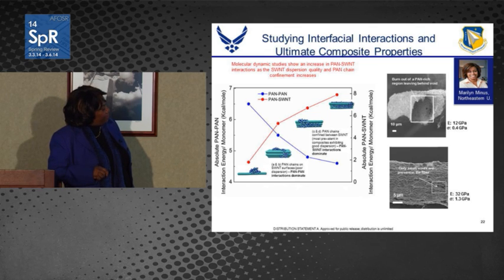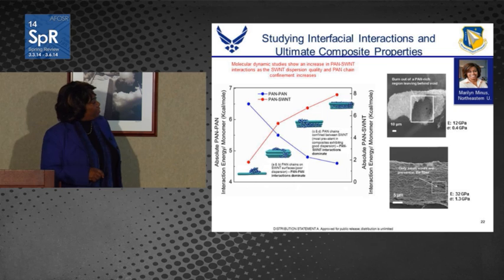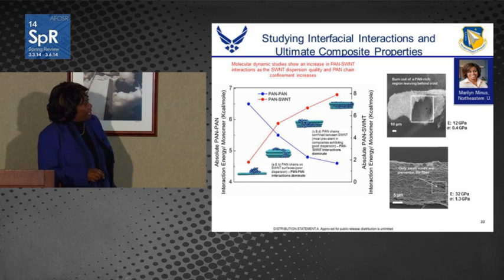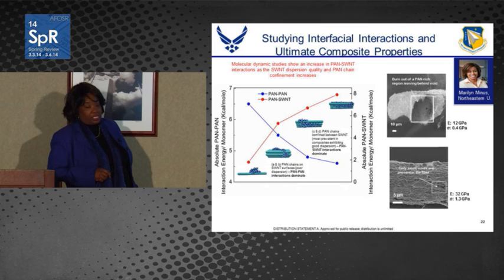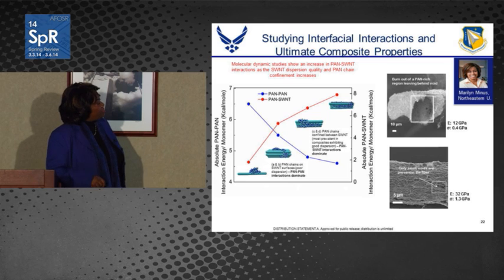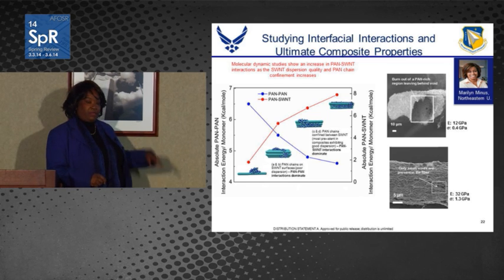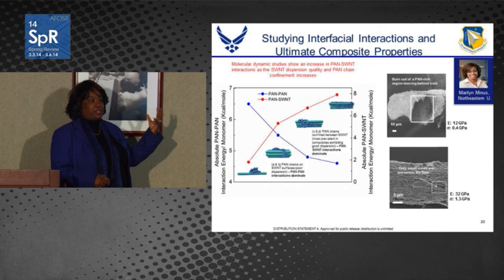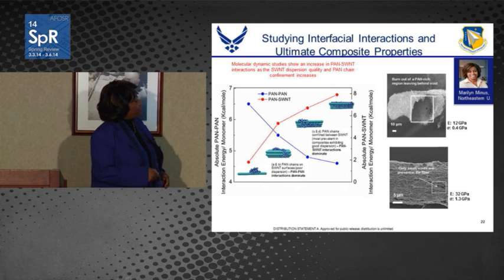And so when you have very poor interaction between the nanotube and the polymer, you get properties like this, where you get burnout, holes, just not very good integrity and correspondingly low mechanical properties. But if you can get really good dispersion quality, that correlates with very nice properties after you take it through the process of graphitization. And so this, I think, is very important work, because it will allow us to begin to quantify the quality of dispersion and ultimately relate that to properties that you could get from materials like this.